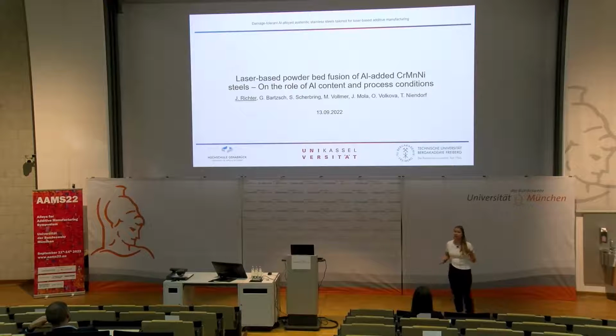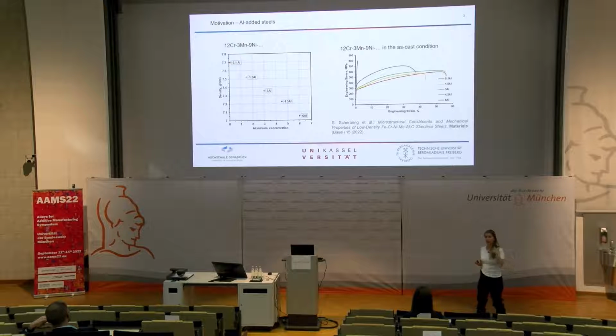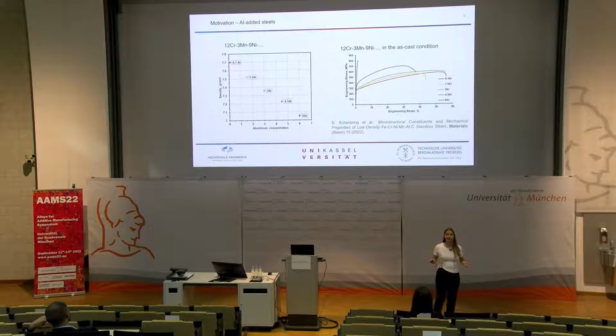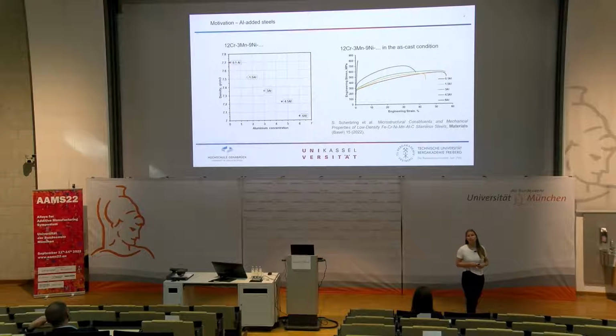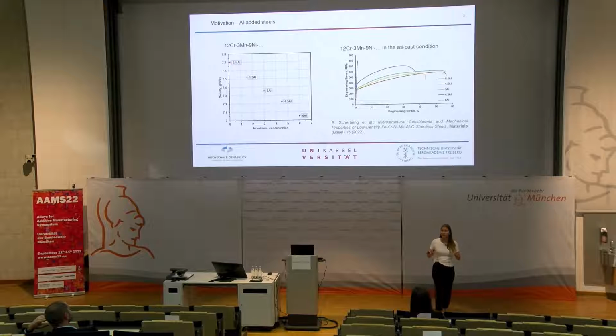So what is the motivation of adding aluminium to austenitic steels? Basically, I want to come from the conventional processing side. When we add aluminium to austenitic steels, for sure, we change the density of our material. In our research, we look at the aluminium content starting from 0 up to 6%. If we change this content of aluminium, we decrease our density by nearly 0.7 gram per cubic centimeter. So this is the total idea, that we can have a lightweight design with a concomitant